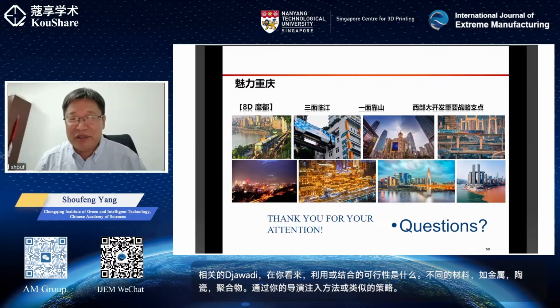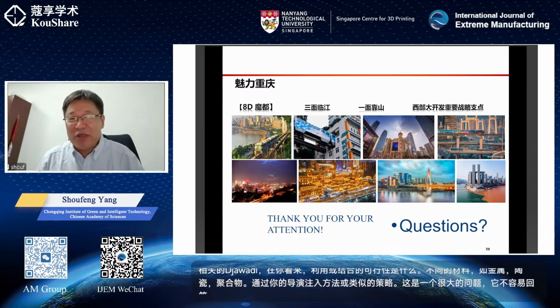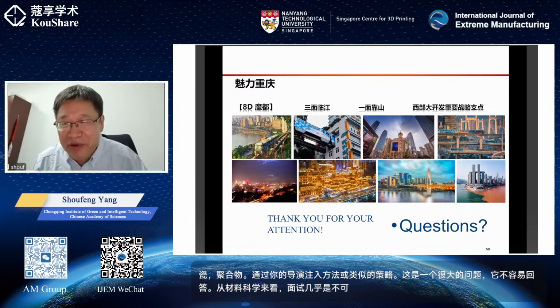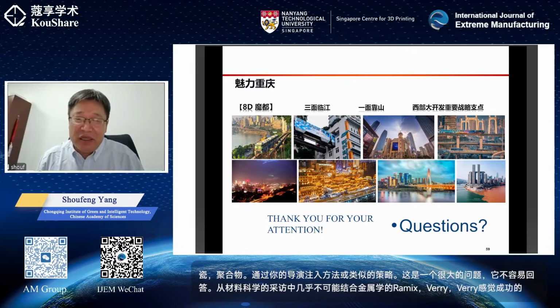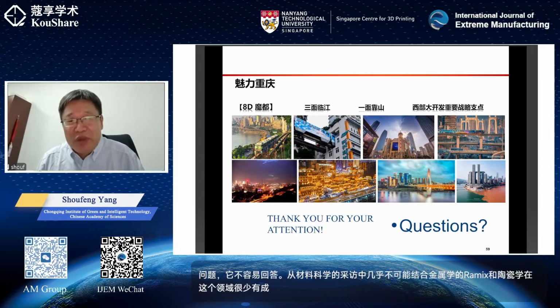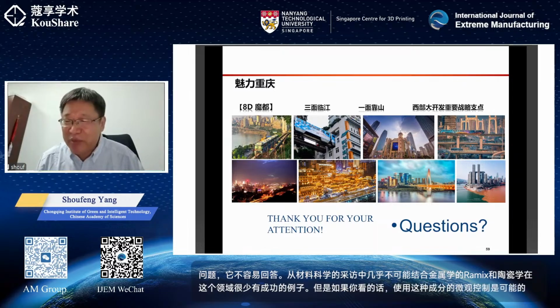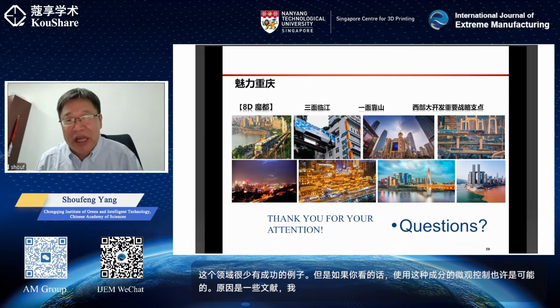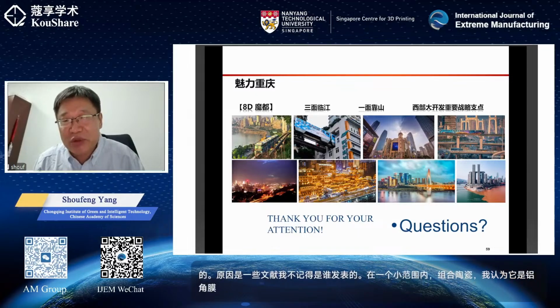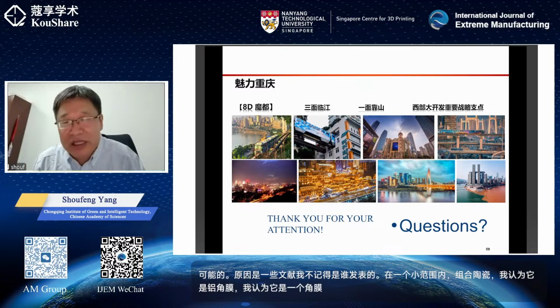That is a big question. It's not easy to answer. From a material scientist's point of view, it's almost impossible to combine metal and ceramics. Very, very few successful examples in this area. But using this micro control of the composition might be possible. If you look at some recent literature, I can't remember who published that, at a small range, they combined ceramics, I think it's alumina or zirconia, and some metals successfully together, but not in a big range,